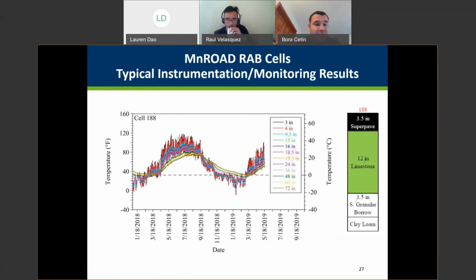And here are the soil temperature readings at different depths that Raul mentioned, from the 3-inch depth all the way to 72 inches depth in each test section. This is for the temperature variations for the test section built with 12-inch thick limestone. And as you can see, it fluctuates a lot, and it goes below 0 degrees Celsius, the freezing line, and it stays frozen during that period of time, then it thaws.